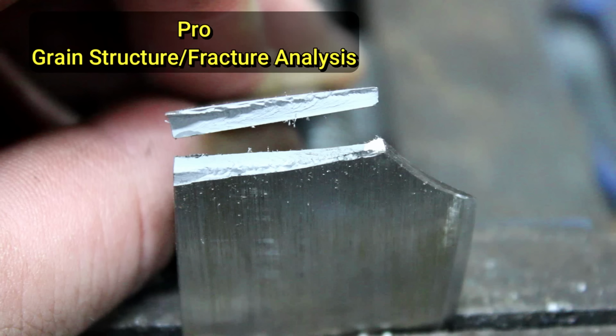On these last tests, we're not just seeing failure in the blade, we're seeing tearing and separation through the tang as well. That points to the tang being too hard and too brittle, instead of having the toughness it needs to absorb that load. What's happening here is we're getting a more uniform hardness out of the kiln process. The entire piece, including the tang, is transforming and tempering evenly, which sounds good, but in practice it removes the softer and tougher zones you actually want in the tang and along the spine. With the flame temper, we're naturally correcting for that. We're putting more heat into the tang, bringing it up through the spine, and feathering it forward across the blade. That step isn't happening on the kiln side.